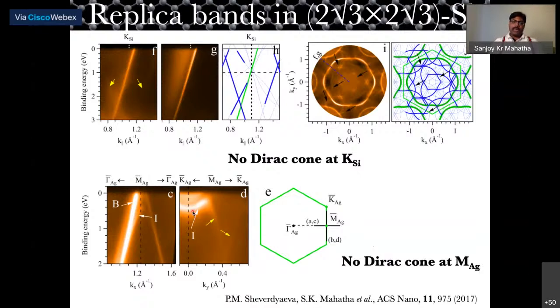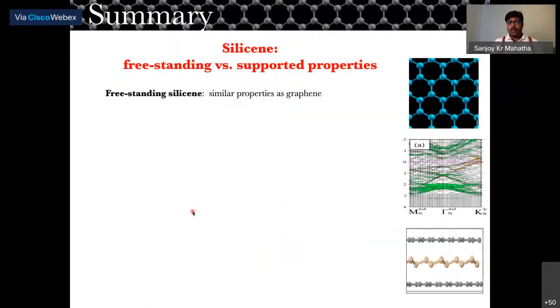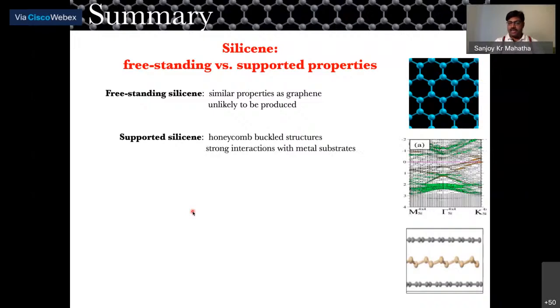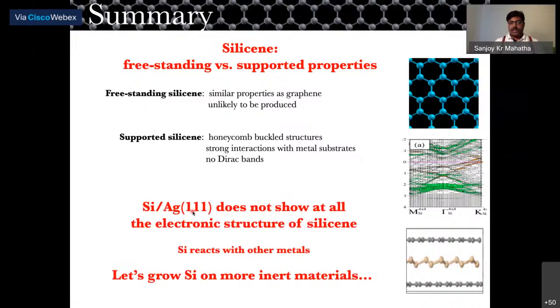So from here we said that on freestanding silicene we expect similar properties as graphene, but it is very unlikely to be produced. So then we did supported silicene, which has a honeycomb buckled structure, which is okay, but there's a strong interaction with the metal surface, strong hybridization with silver 111. And there is no Dirac band. So from here we can say that silicon on silver 111 does not show at all the electronic structure of silicene. There is no Dirac cone.